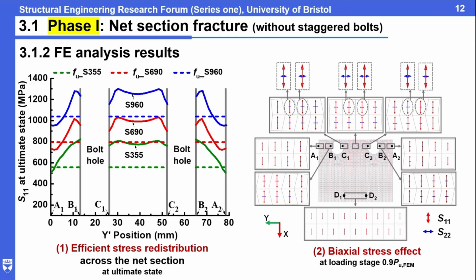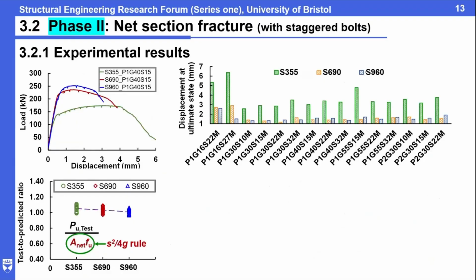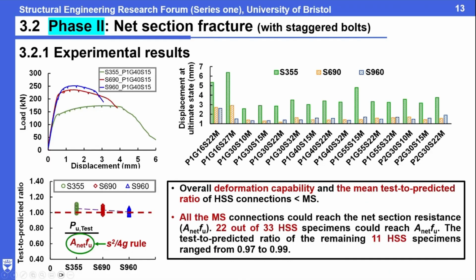Okay, this is phase 1. And then phase 2. In phase 2, because we wanted to make the analysis consistent, we also compare the ductility first. No doubt high strength steel is lower than the mild steel. And then when we compare the test to predict ratio, if you plot the line here, you will find that for S²/4G some are lower, right? So that's why we also need to analyze this.